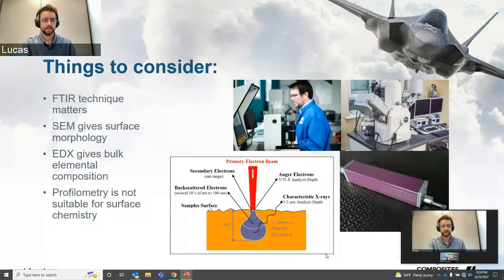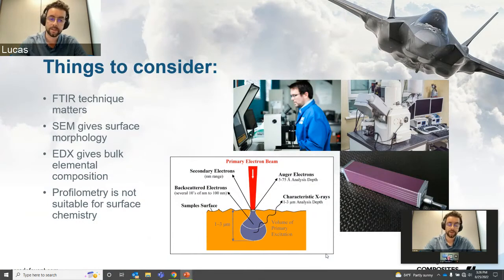Okay, a couple things to consider with some of these measurement techniques. The FTIR technique matters. Most people that have access to FTIR are doing ATR. It can be good. It's good for compound identification, but the problem with ATR is you're sampling down in the bulk material, like a micron or two. So it's actually not telling you, if you remember, we really care about the top 1 to 15 to 20 molecular layers of that surface.